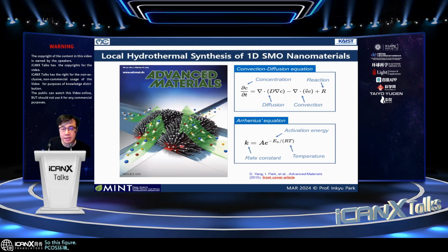So this figure is actually a cover figure from Advanced Materials, which was published about 9 years ago. You can see here, as we make some electronic device, we can design it such that if we apply electric potential across these two points, they will be locally heated to generate Joule heating. And this Joule heating will generate heat transfer, convective heat transfer, and because of the convective heat transfer, mass transfer is also accompanied inside the liquid precursor environment.